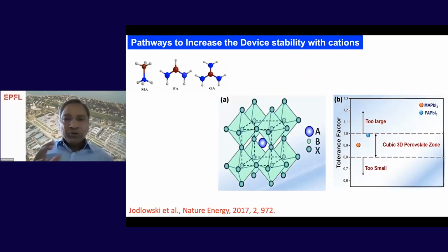So let's take the compositional engineering of perovskite material. The basic formula is ABX3, where A is a cation. There are three types of cations here that I have taken: methyl ammonium, formamidinium, and guanidinium. As you can see from these three cations, one has one amino group, two amino groups, three amino groups. These amino groups form hydrogen bonds with the iodide groups. So the number of amino groups enhances the stability of this composition. That's one of the logic.